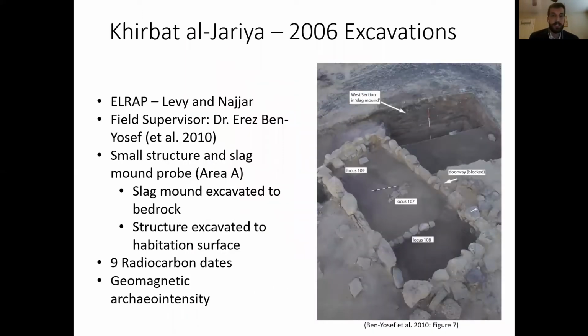So starting with the 2006 excavations, as mentioned, this was an ELRAP project directed by Tom Levy and Mohammed Najjar, and Dr. Erez Ben Yosef functioned as the field supervisor. The excavations included a small structure and a slag mound probe. You can see both of these in the photo on the right. The structure was delineated and excavated down to a habitation surface, but its exact function wasn't clear. And the slag mound probe was excavated down to bedrock, giving a record of metallurgical production in this part of the site. The project also collected 9 radiocarbon dates and some slag samples for a geomagnetic archaeointensity study.